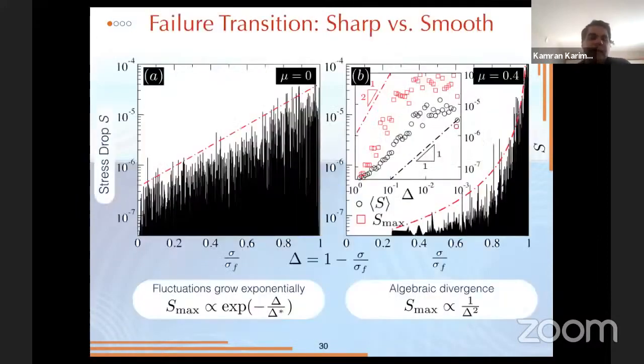I also did some stress-based tests, where we only control the stress, much like a creep test, and we increase it at a constant rate and see how the signal, which is the stress drop here, evolves as a function of distance to the critical point.